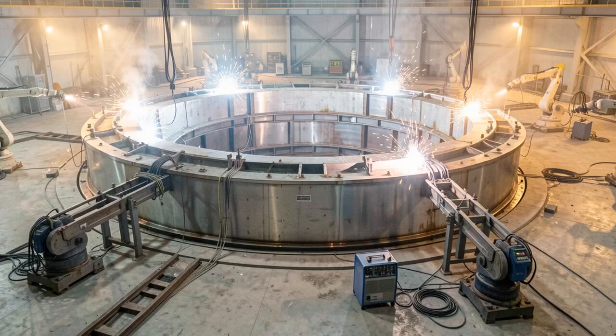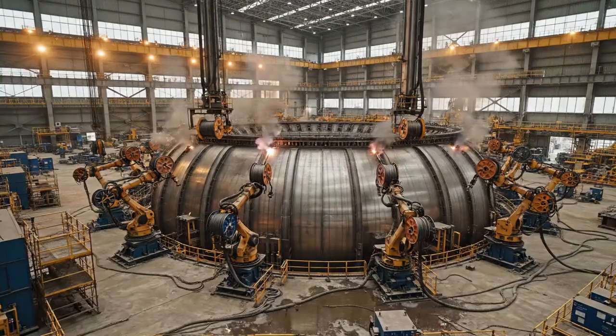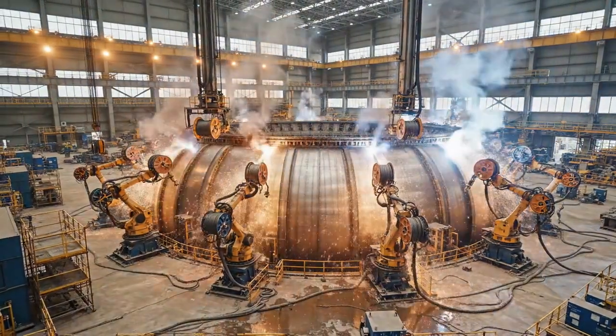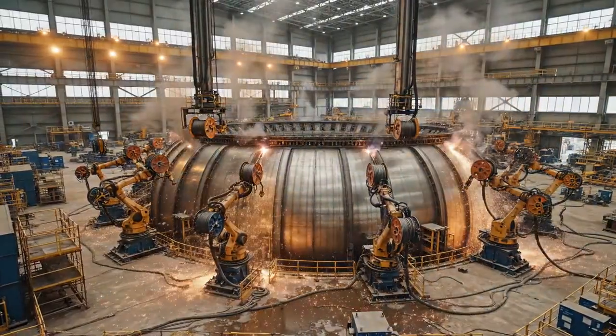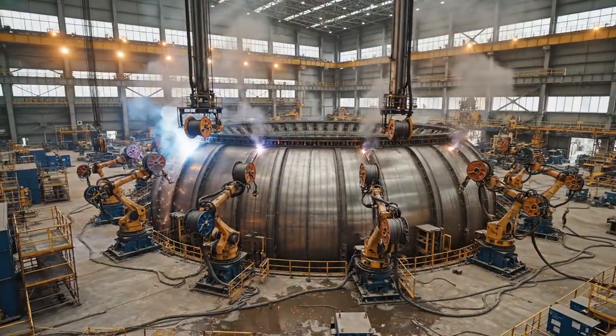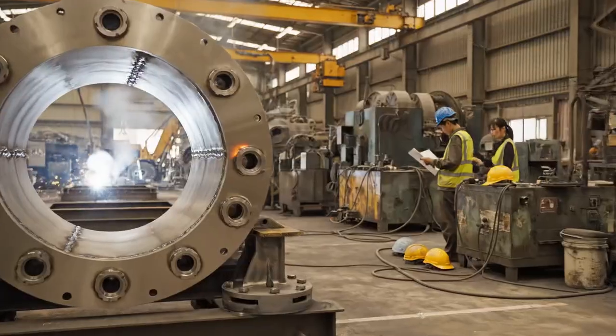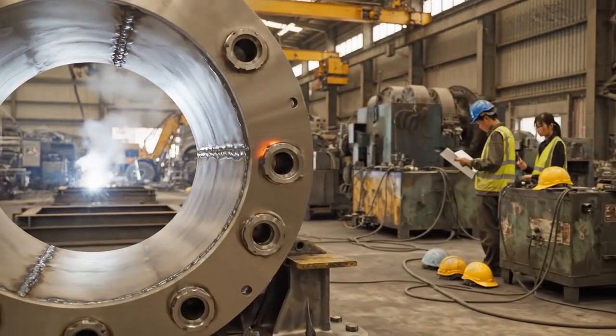The finished vessel must hold a vacuum 10 times more complete than the vacuum of outer space. A single small porosity in a single weld will destroy the vacuum. Every weld is inspected by X-ray and ultrasonic testing before the next weld begins. Weakness is not an option.